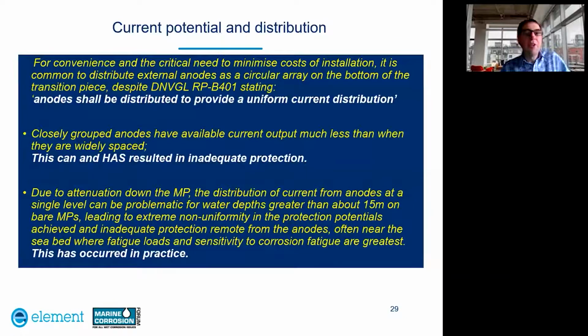For convenience and the critical need to minimise costs of installation, it is common to distribute external anodes on a CP system as a circular array on the bottom of the transition piece, despite DNV GL recommended practice B401 stating that anodes shall be distributed to provide a uniform current distribution. Closely grouped anodes have available current output much less than when they are widely spaced. This can and has resulted in inadequate protection of offshore wind structures. Due to attenuation down the monopile, the distribution of current from the anodes at a single level can be problematic for water depths greater than about 15 meters on bare monopiles.